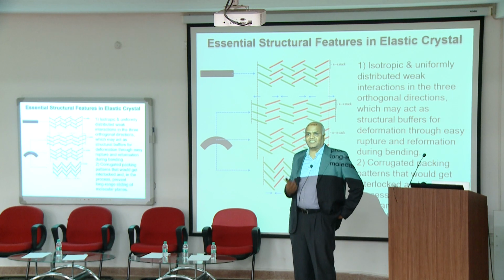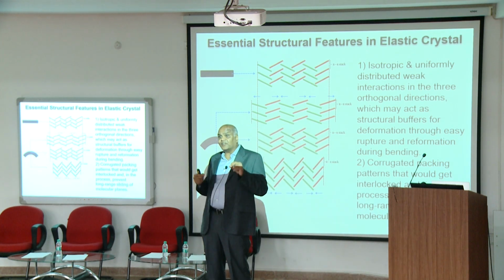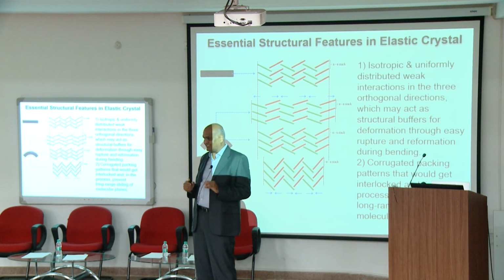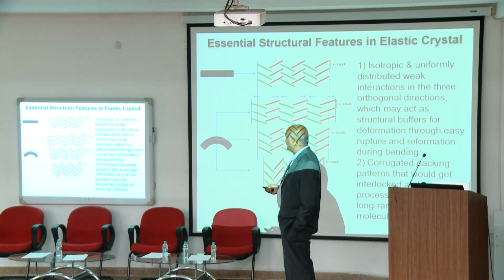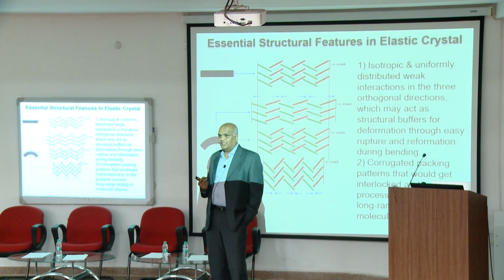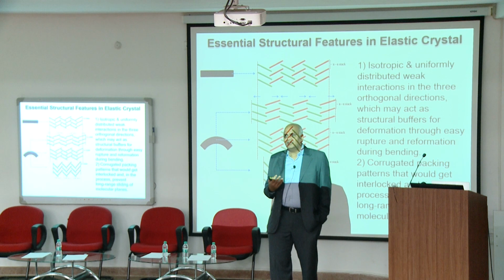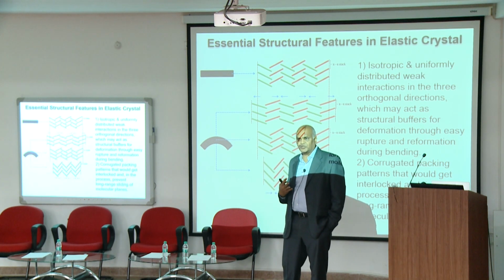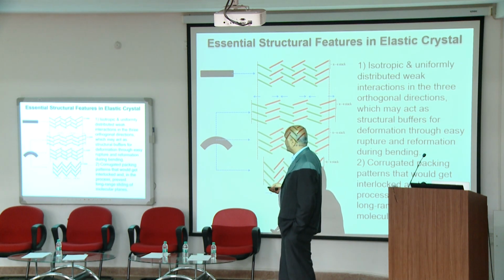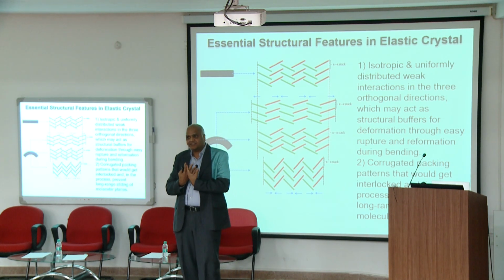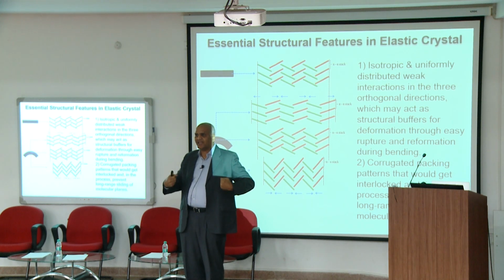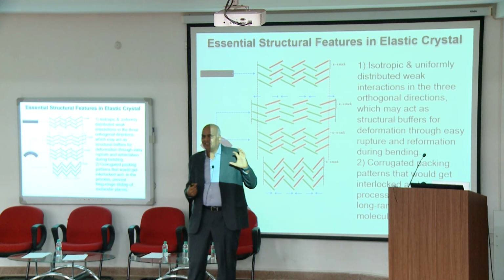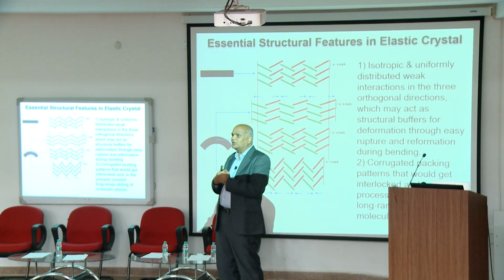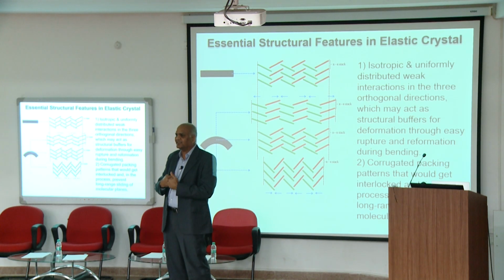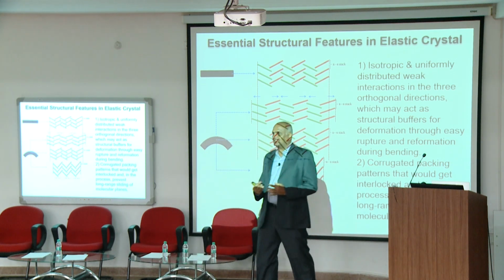So what are the essential structural features that will give you, for an organic crystal, not metallic crystal, very high elastic flexibility? Basically, you need two features essentially. The first one is you should have a large number of weak intermolecular interactions in all the three orthogonal directions. Okay, they should be dispersive and isotropic. So what happens is, in metals, the bonds get stretched when you apply stress within the elastic regime. In the organic crystals, because the molecules are bound by weak interactions, these interactions break and reform. There is no problem with that. So they act as a buffer for the applied stress, and that's how you get large compliance in the system, good elasticity.